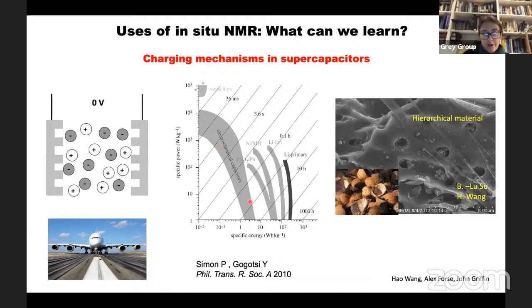What they're known as, supercaps or electrochemical capacitors, consist of these carbons that are highly porous, and then when you charge them up, you store charge in the form of a double layer. So this is charged positively, then you store negative ions on the carbons. And this is an example of the type of structure that you have. It's very hierarchical. They're activated carbons made out of coconuts. You activate it to get these sort of holey structures that are good because you allow the materials to go in. And this is a binder that's pulling the whole thing together.